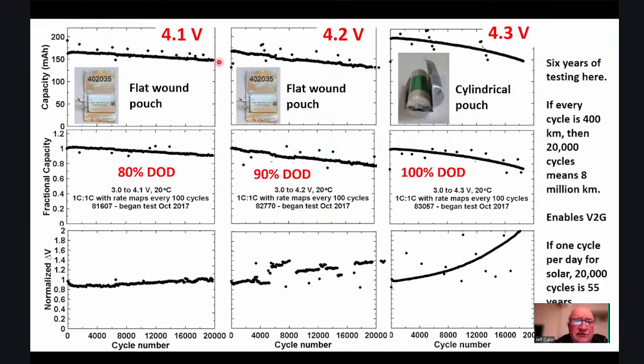The reason that you would go to higher voltage is you can get larger capacity at the beginning. But these would have driven a vehicle 8 million kilometers, 8 million kilometers. So you can do 100% depth of discharge cycling and still get incredible lifetime, okay? And if there was one cycle per day to back up solar, 20,000 cycles is 55 years.